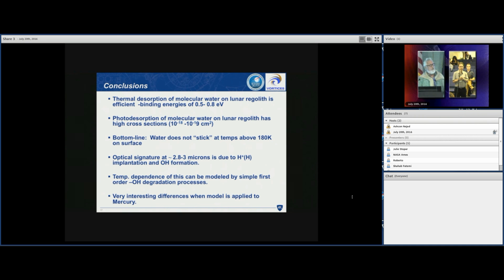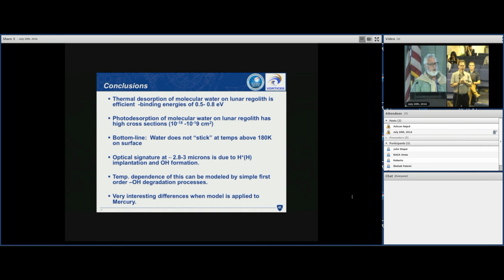Okay, so we don't have an activation energy for diffusion. We just put in that diffusion constant, right? But we do have some activation energies where we're looking at the rates of the first order loss processes. In those cases, we put in an activation energy related to charging of grains. We put in the activation energy to release a trapped electron, and that's about 0.2 eV. Other than that, there are no other activation energies.